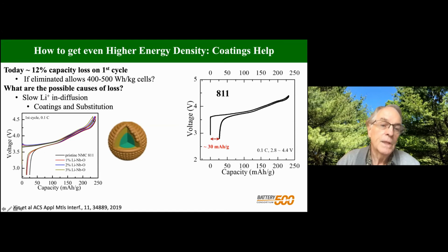And I think you can see this at the 1% level did no damage to the total capacity on charging, and it reduced the first cycle loss by about 40%. And this is at room temperature. If we go to higher temperature, this is further reduced. So we believe by appropriate substitution, this first cycle loss can be reduced. We know with aluminum it's reduced a little bit, but not by as much as using niobium. So we believe you need to do substitution and coating.